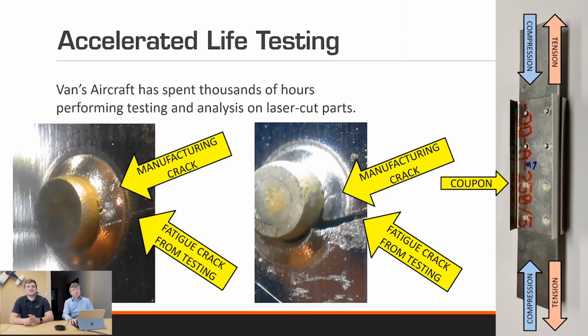So effectively, what we learned through this testing is that the fatigue performance was not impacted by these dimple cracks, these manufactured cracks created at the time of assembly. There were only a handful of instances where this cracked dimple connected with any fatigue cracking in test, and through that, there was no statistically detectable difference in the performance of these holes.